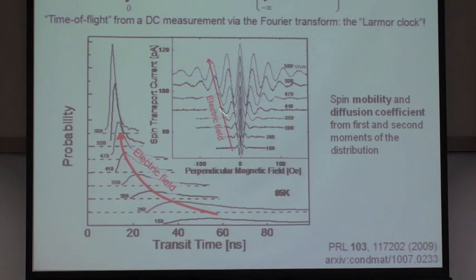And if we take the transform of this data, then we can see the empirical spin current transit time distributions that result. And they, of course, correspond to our understanding in that both the mean of the distribution decreases under the influence of stronger electric fields because the electrons are moving faster, the drift velocity is faster, in higher electric fields. But also, the uncertainty in these distributions gets smaller and smaller because, once again, you're minimizing the effects of diffusion and hence dephasing.